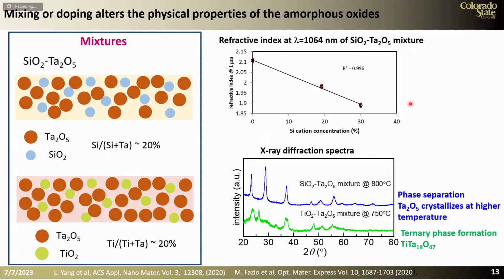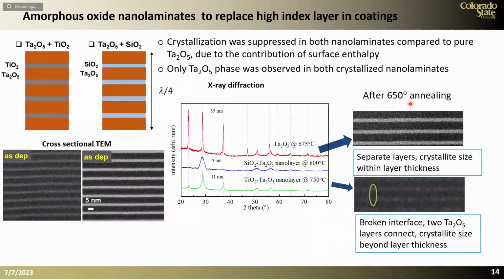And you can do that by doping the material with another oxide. In addition, what we have learned is that every time we mix two oxides, we actually increase the crystallization temperature. And this is beneficial for both our efforts in high power lasers and in ultra stable coatings for LIGO.